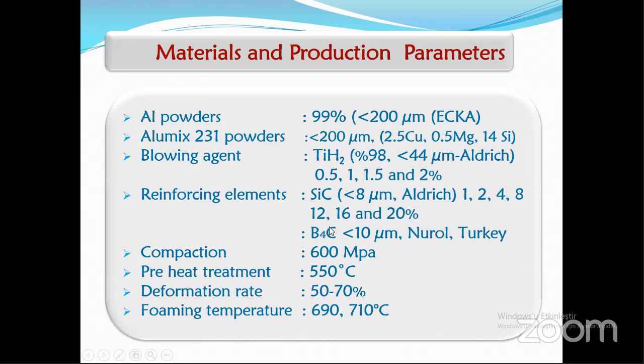We work a lot, actually, so I will just give some information about that. We use aluminum powder and Alumix 231 powders from ECKA. As blowing agent, we use titanium hydride from Aldrich. Reinforcing elements: silicon carbide from Aldrich and boron carbide from Nurol, Turkey. Compaction was 600 megapascal. Preheat treatment 550. Deformation rate 50 to 70%. Foaming temperature 690 to 710 centigrade.